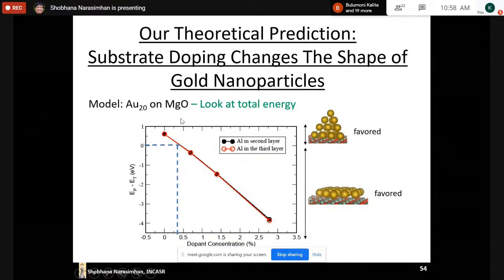And we showed that if you calculate the total energy of this gold nanoparticle as a function of the doping concentration, then beyond a certain doping concentration, the planar form is favored over the three-dimensional form.